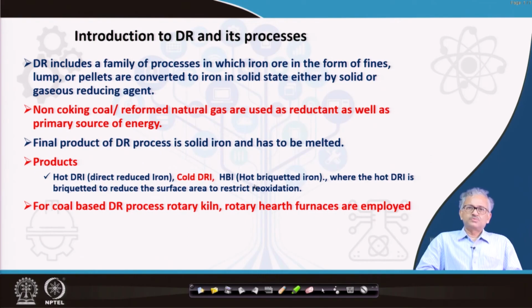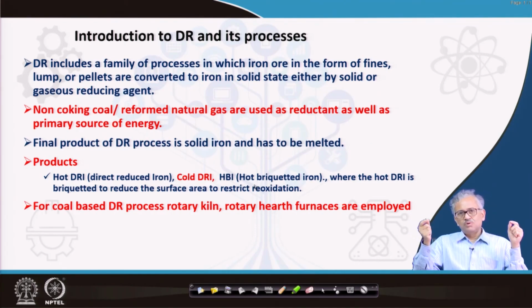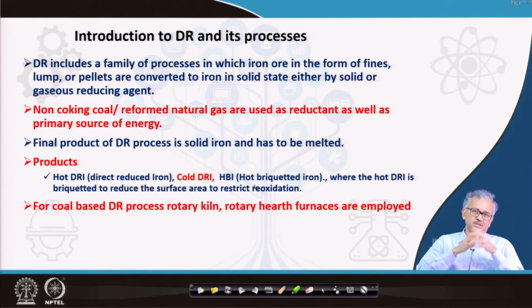And what are the reactors you use for coal based DR process? Mostly the reactor that is used is called the rotary kiln. It is basically a cylindrical reactor, inclined with the horizontal such that the material can move under gravity while rotating. So some inclination is required, and it is a simple cylindrical reactor. You burn the coal from the exit; you give air and coal and burn it. The coal burner generates the heat, and carbon is also used as a reductant. Carbon generates CO in situ and it reduces the iron ore by taking the heat from the furnace atmosphere. This is the process in case of the rotary kiln.